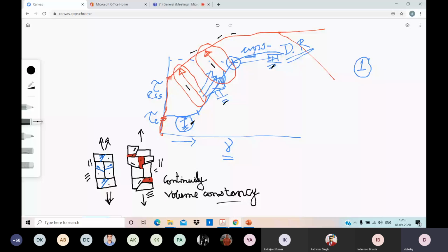As they deform individually, there will be either voids, that is discontinuities, or there can also be an overlap, where one part of a single crystal pushes inside another part of a single crystal. There can be either void or overlap.